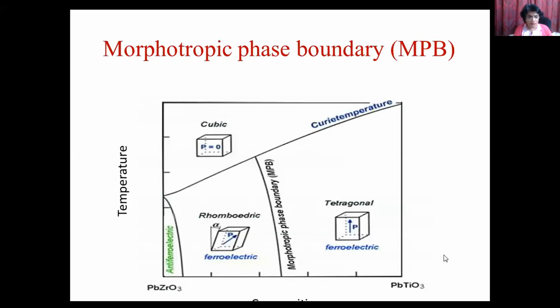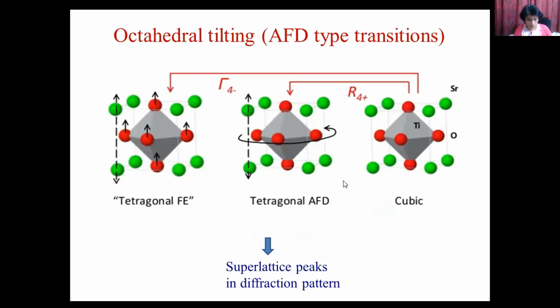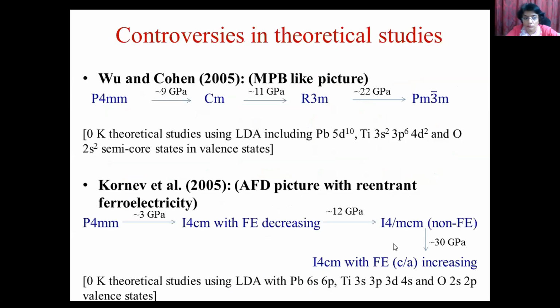Now, what is MPB? For those who are not familiar with this, in the composition-temperature phase diagram, we have a vertical line in which, for a broad range of temperature, just by changing the composition, we get the structural phase transition. This is known as MPB or morphotropic phase boundary. Now, AFD transitions occur because of the rotation of the oxygen octahedra. Because of this oxygen octahedra rotation, the unit cell gets multiplied and we get superlattice peaks in the diffraction patterns.